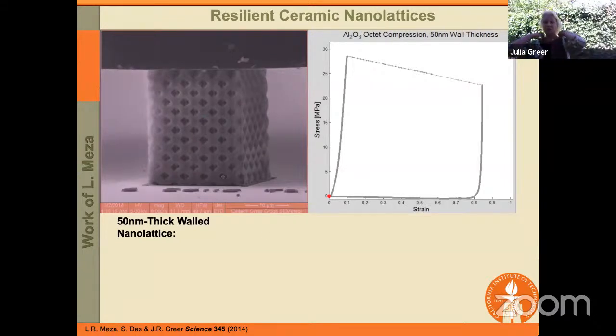So what I'm about to show you is a nano architecture. This specific one is called an octet architecture. It's made out entirely of hollow tubes with alumina. So alumina is a very brittle material, of course. The wall thickness is on the order of 50 nanometers and the tubes are all hollow. So it's effectively your coffee mug with a severe case of osteoporosis. So it's very porous and it's very brittle.